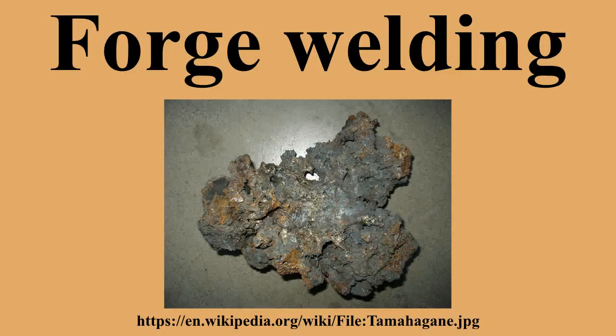After smelting, the sponge iron needed to be welded, or wrought, into a solid block to squeeze out air pockets and excess slag. Many items made of wrought iron have been found by archaeologists that show evidence of forge welding, which date from before 1000 BC. Because iron was typically made in small amounts, any large object, such as the Delhi pillar, needed to be forge welded out of smaller billets. Forge welding grew from a trial-and-error method, becoming more refined over the centuries.